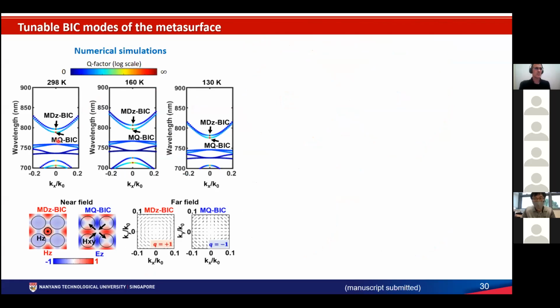We started doing numerical simulations to design the structure, and we designed a structure that has two resonances, a magnetic quadrupole and a magnetic dipole BIC. And as you can see, they lie very close to each other. By changing the temperature, which will also induce a change in the refractive index, you will see that the modes of the structure will shift in wavelength. And here on the bottom, you can see the modes of the structure in the near field and also the associated polarization, where you can see there's a topological charge of +1 for the magnetic dipole and -1 for the magnetic quadrupole.